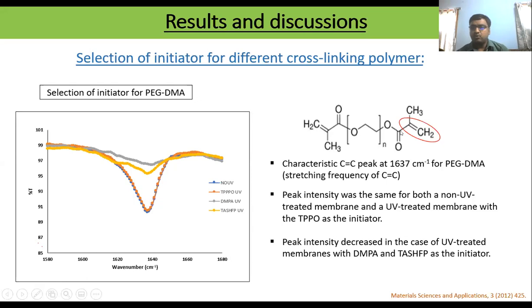So as you move towards more cross-linking, we reduce the number of carbon-carbon double bonds. That is depicted over here in this FTIR spectra. When we have more C double bond C, then we get this peak, but as it gets reduced, this peak is getting flat. So we can see from this result, these two initiators, DMPA and TASHFP, work here. So from this, you can say DMPA is better for the PEG-DMA cross-linking agent. TASHFP also works because this was the preliminary study.